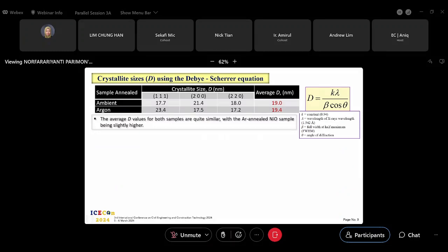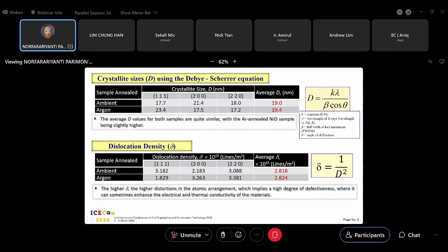Then we calculate the crystallite size of each sample and get the average crystallite size. Both samples are more or less the same size, with the argon-annealed nickel oxide sample being slightly higher, at 19.4. We use the Debye-Scherrer equation to calculate the crystallite size. In terms of dislocation density, for the three prominent peaks, we calculate and it shows the same trend, with argon slightly higher than ambient.